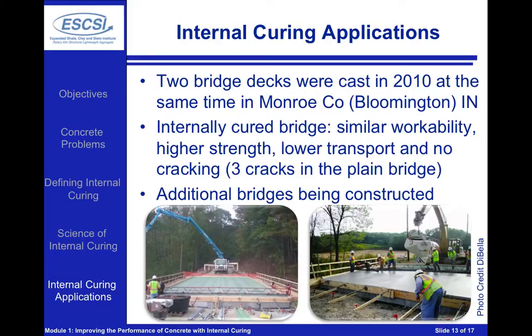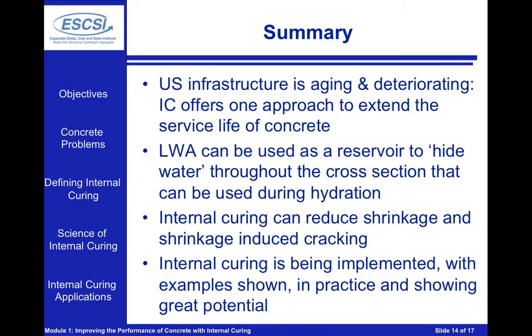The internally cured had slightly lower diffusion coefficients, but really I think one of the telltale signs was the internally cured concrete contained no cracks, while the plain concrete contained three cracks in the bridge. So the plain concrete, three cracks, the internally cured concrete had no cracking. Now, does this mean that internally cured concretes will never crack? No. However, what we can say is that we're substantially reducing the potential for cracking when we use internal curing.